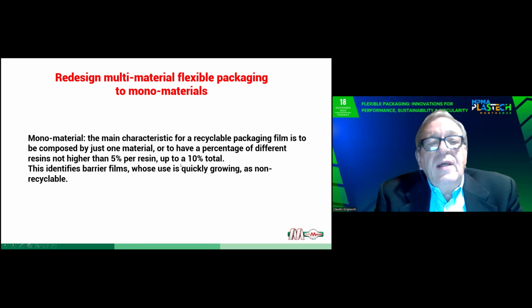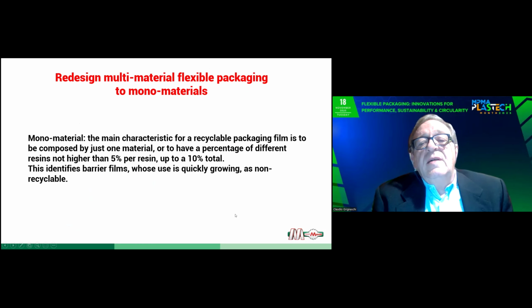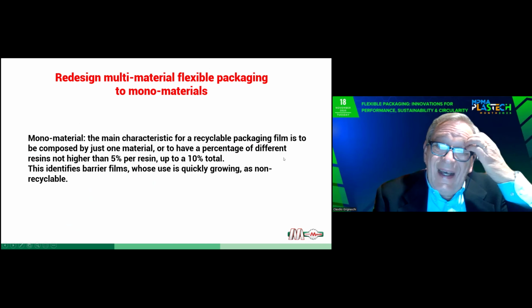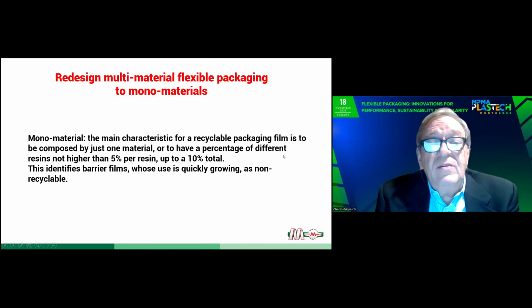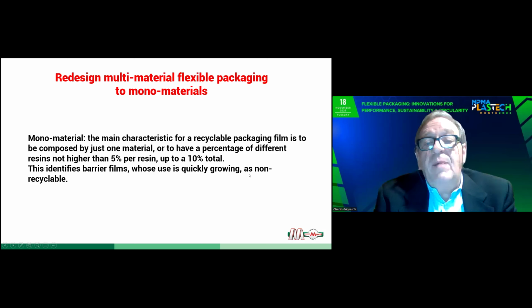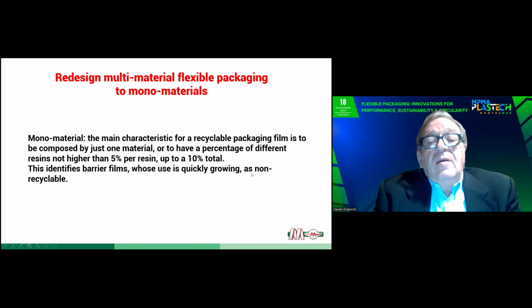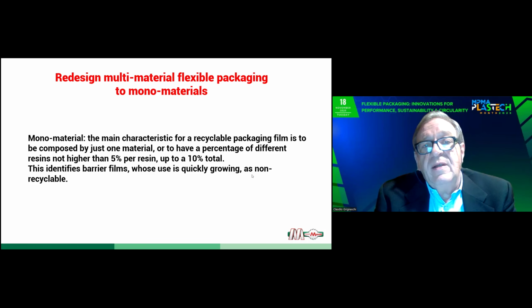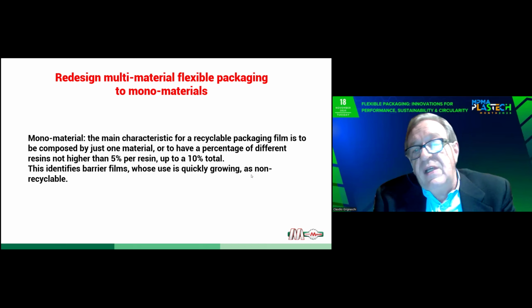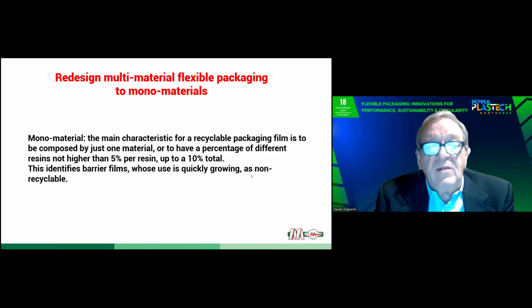Talking about monomaterial, the classical definition is that a packaging film to be identified as monomaterial must have a maximum percentage of different resins not higher than 5%, up to 10% total. This, of course, phases out most co-extruded barrier films, whose use is quickly growing, as they are non-recyclable because the barrier layer is usually 6, 8, 10% of the overall structure.